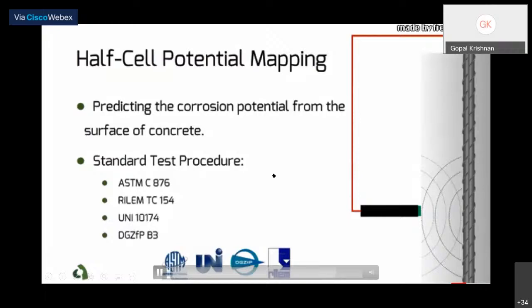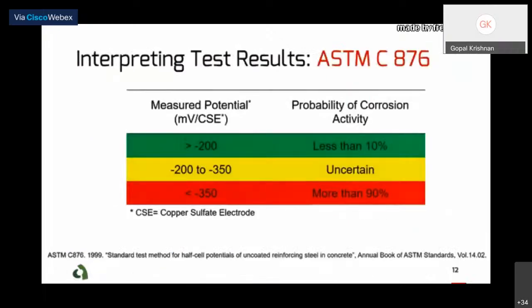The value is normally presented in contour plots, showing different half-cell potential values. This helps identify areas with a higher chance of corrosion. For example, ASTM C876 introduces 3 different ranges for the measurement. Half-cell potential values less than negative 350 millivolts, measured in reference to copper sulfate electrode, represent an area where probability of having active corrosion is more than 90%. When measurement is higher than negative 200 millivolts, this probability is less than 10%. Results for half-cell potential values between negative 200 millivolts to negative 350 millivolts is uncertain.